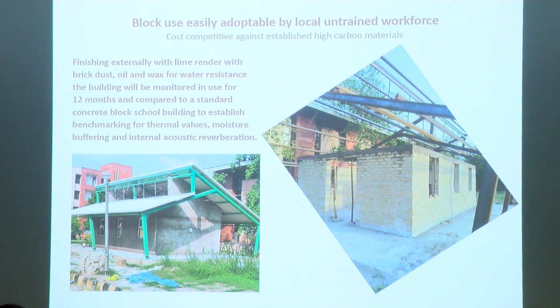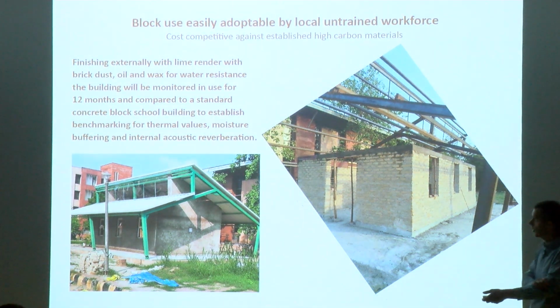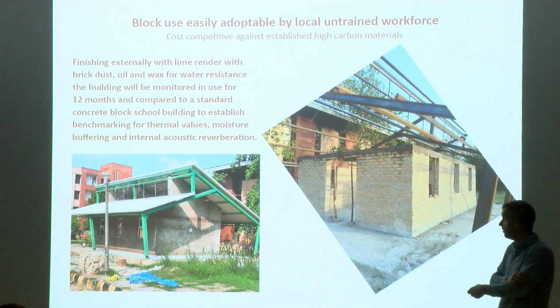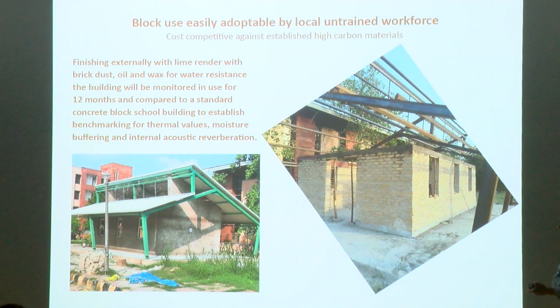And here are a couple of photos which are halfway through. We finished externally with a lime render with brick dust, oil and wax for water resistance. And as I mentioned before, we are monitoring for 12 months and benchmarking thermal values, moisture buffering, and internal acoustic reverberation. We have got very good acoustic results on the material as well. The fibers help the acoustic absorption, which reduces reverberation, especially in areas where traditional materials are not that good performing. So just having a percentage of the wall built with this material will help with acoustics as well.